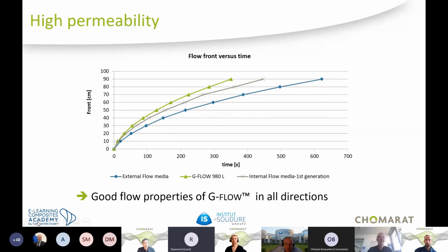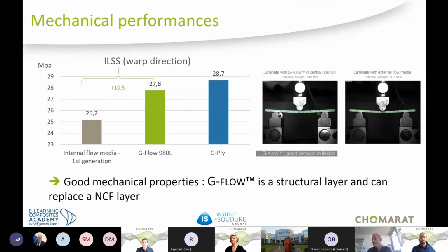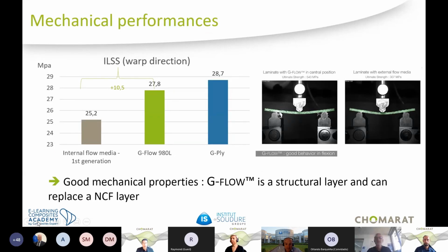On this graph, we compare the flow, the permeability of the G-Flow versus other flow media. The study has been done with the same glass ratio. This graph shows that the G-Flow is an excellent flow media. Now, we show the technical properties of G-Flow in interlaminar shear strength. Once again, the study has been done with a laminate having the same glass ratio.